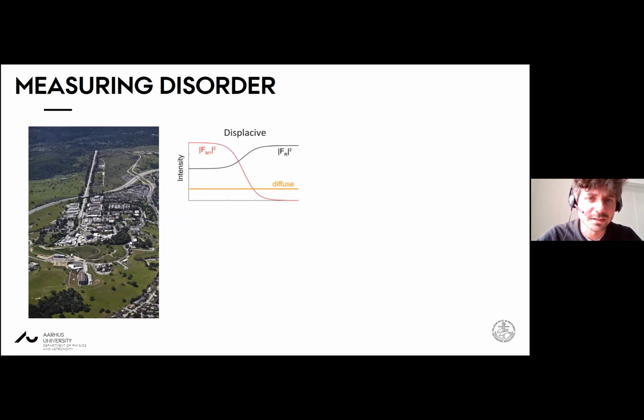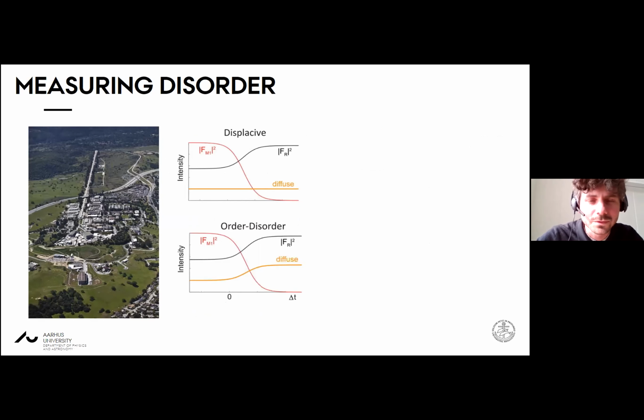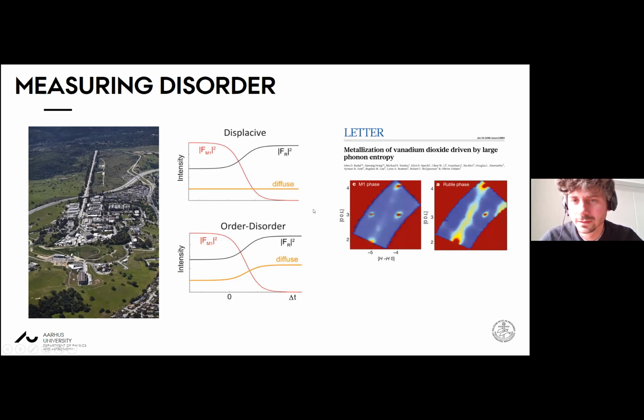So we went to LCLS in Japan. And just to reiterate what we expect to see: we went to LCLS in the USA, at Stanford, and we look for certain peaks that are going to go down in intensity, and certain peaks that are going to go up in intensity. Whether this is a displacive transition or an order-disorder transition will depend on whether the diffuse scattering goes up or stays the same. Okay, so that was that slide.